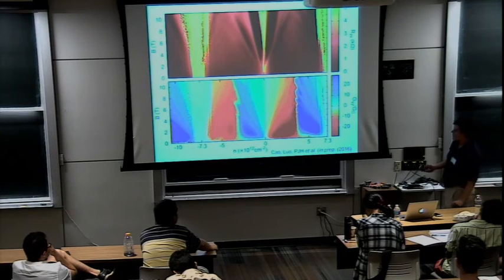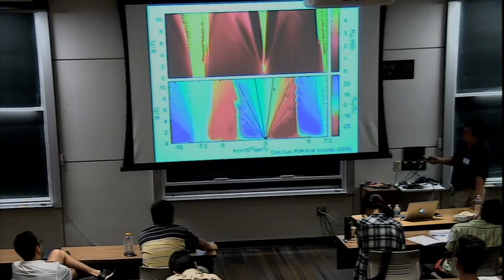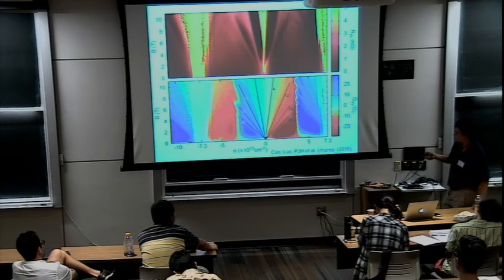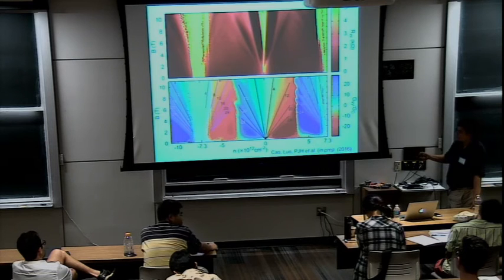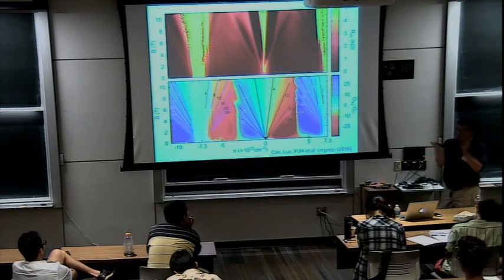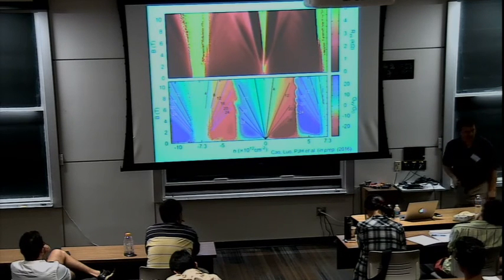Okay? You can measure what are the filling factors for which conductance plateaus appear. For the original, at very low energies, it still looks like graphene, like massless Dirac. 4, 12, 20, 28, just twice graphene. But if you go to these bands, it actually looks like massive electrons, because these bands have mass. They're not massless, okay? Up there, etc., and many more things that we're measuring.